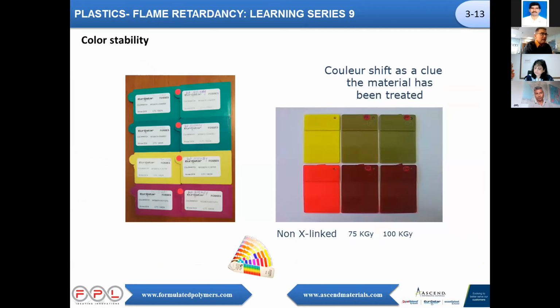Then I would say, is there any change on your plastics? Yes, there are. Because when you do the irradiation, there is a slight elevation in temperature on your material, and sometimes it can change the structure of a material. So we have the knowledge to make very nice and fancy colors that remain stable after irradiation. The red dot is a clue that the material has been irradiated at 100 kilogray. So we can design stable greens, stable yellow, stable purples.